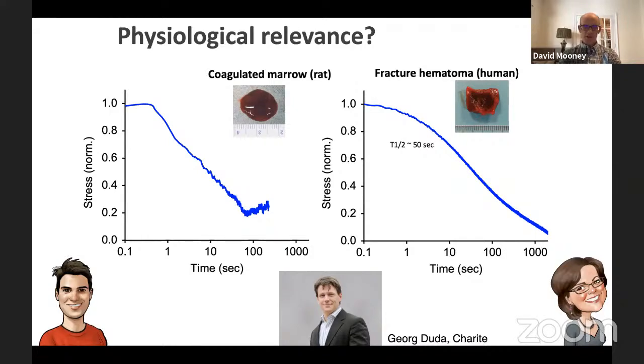And so if we look at either coagulated bone marrow on the left, or fracture hematomas that are removed from human patients coming into the Charité Hospital for revision surgeries on the right, you can see if we do a stress relaxation test, these materials are viscoelastic and actually exhibit stress relaxation behavior that quantitatively is very similar to that which we found empirically to be optimal for osteogenesis, suggesting that what we're really doing is rediscovering the microenvironment that our body normally uses to drive osteogenesis during bone regeneration.